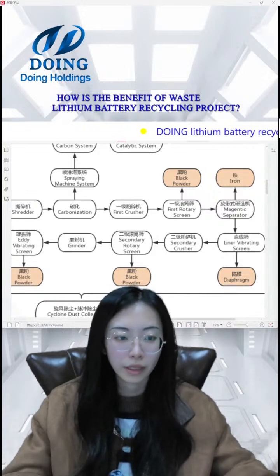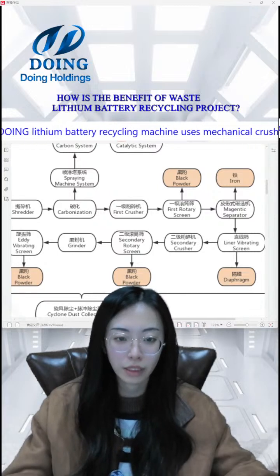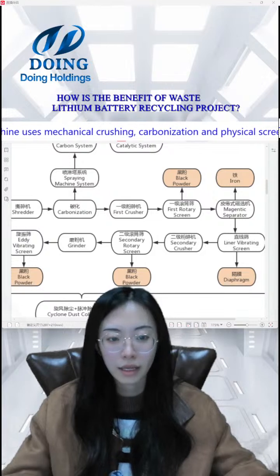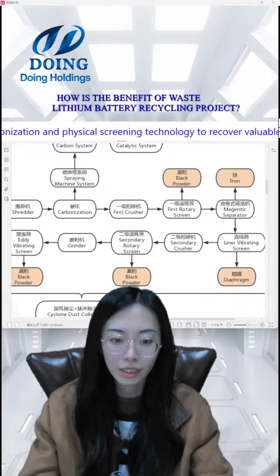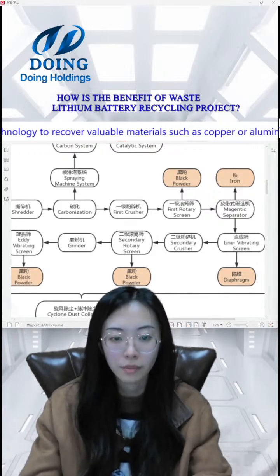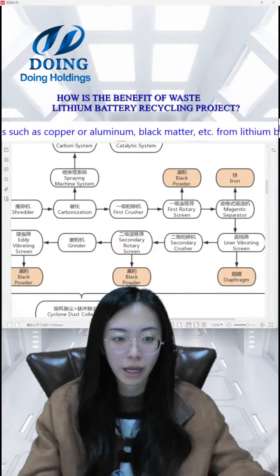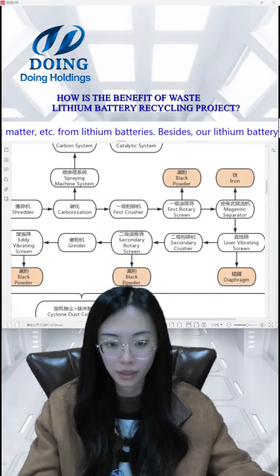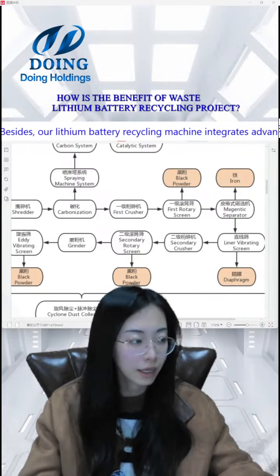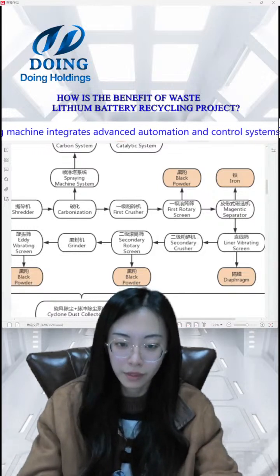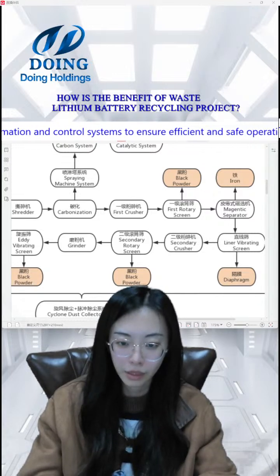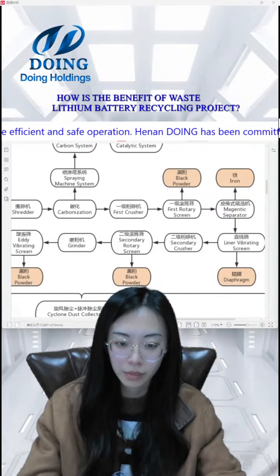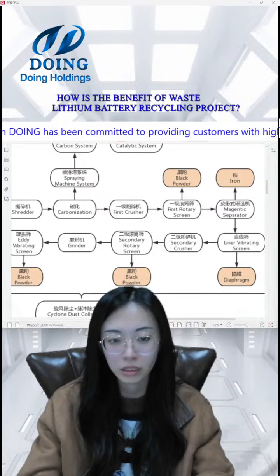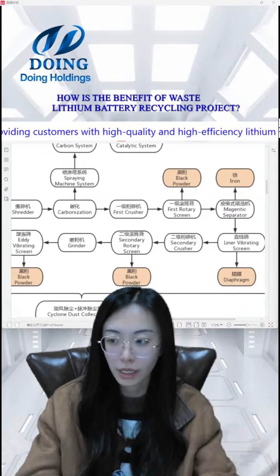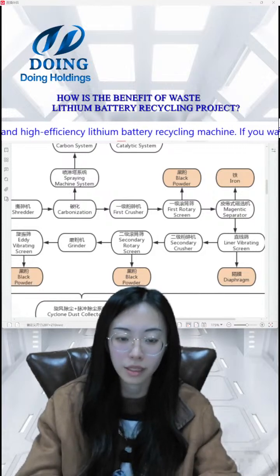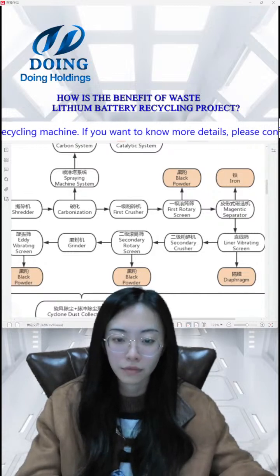And this step is to separate the diaphragm. The linear vibrating screen uses vibration for screening and controls different products through the multi-layer screen mesh, which are just discharged by their respective outlets. The two layers of the screen mesh are, the first one is 2 mm and the second one is 100 mesh. They are stainless steel. The top layer of the screen are diaphragms, and the middle layer is the copper, aluminium, and the black powder. And the bottom layer is the black powder. So we can not only separate the diaphragm at a separation rate of 98%, but also we can separate some of the black powder. This is a linear vibrating screen.